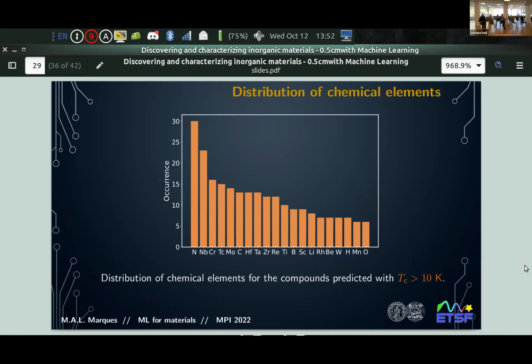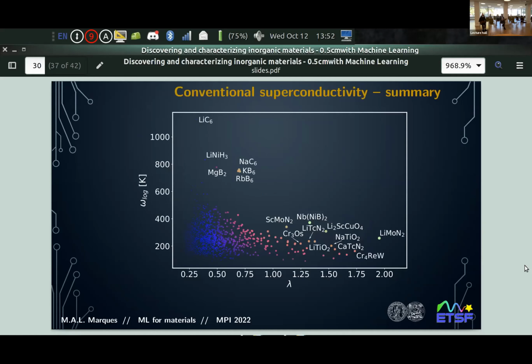This was the first biggest surprise. Then we plotted our compounds. This was also quite interesting. So this is the logarithmic average of the phonon frequency. Here you have the electron-phonon coupling constant, and the size and the color of the points is proportional to the superconducting transition temperature.